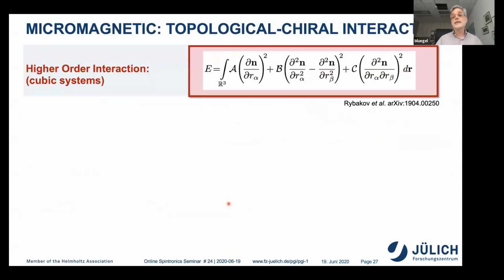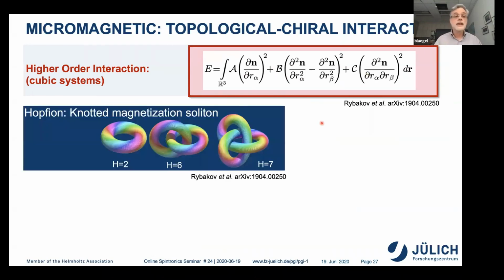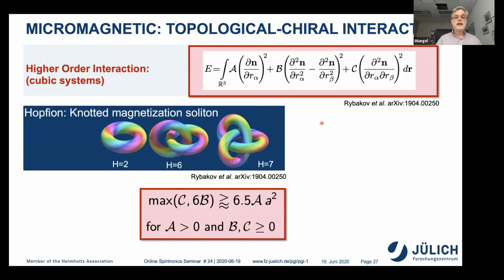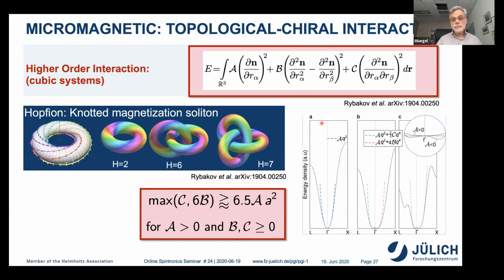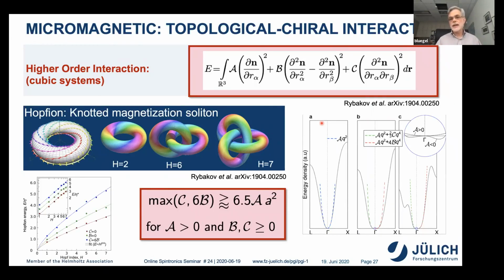And we found, this has been worked out by Rybakov and Kiselev, that if you, for example, have certain higher order terms, depending on the material constants A, B, and C, you can have completely different objects, for example, knotted magnetic excitation solitons of different types, if the parameters are right and you have the right materials. I don't go into this today, but it's a different branching direction, because now we go into three-dimensional particles and not into two-dimensional ones.